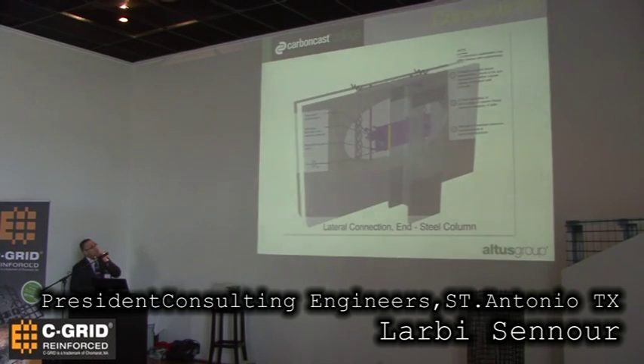Some typical connections, in a sandwich panel, we have to maintain continuity between the insulation in both directions, so we are very conscious of that. So anytime we need much more depth to place a plate or an insert or something like that, we create a trough, thicken and reduce the insulation behind it, so you can place your elements. You take a hit as far as thermal, but at least you have it out to out, top to bottom, and the hit is usually very, very low, 10, 15% reduction in your R value.